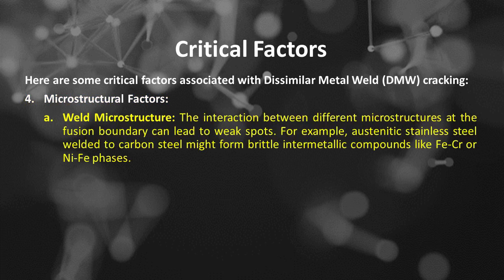The first is weld microstructure. The interaction between different microstructures at the fusion boundary can lead to weak spots. For example, austenitic stainless steel welded to carbon steel might form brittle intermetallic compounds like Fe-Cr or Ni-Fe phases.